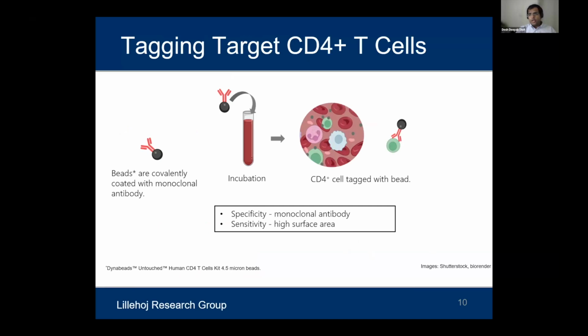As I said, we wanted to quantify cells using a convolutional neural network. It's an optical based technique. We had to somehow tag the cells, because these CD4 positive cells don't look distinct under the microscope unless you stain them or they have some kind of a visual cue on them. So what we did in this research is we incubated these CD4 positive cells with magnetic beads. Magnetic in the sense that these beads are right now available in magnetic form, but we can also have beads which are non-magnetic in nature. These beads are covered with monoclonal antibodies, which makes them highly specific. And when you have micron-sized beads, like 4.5 micron sized beads, you give immense surface area, which increases the sensitivity of the process. So you could tag most of the cells in the sample very quickly when they are in bead form instead of being on a surface.